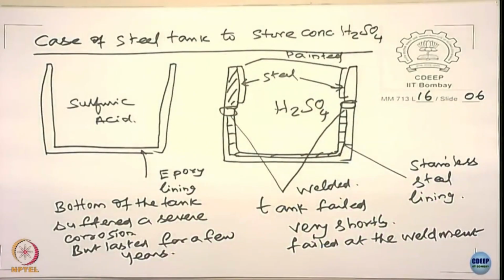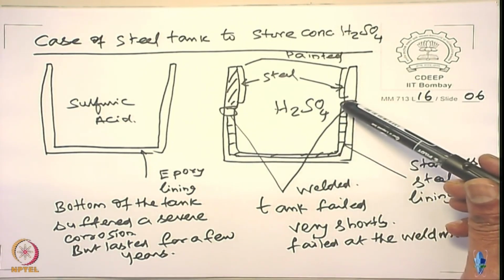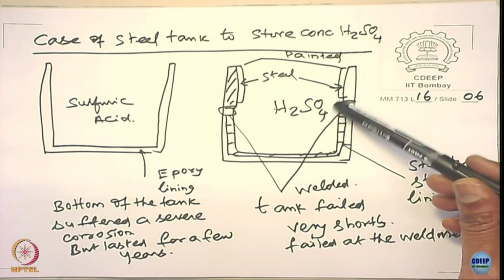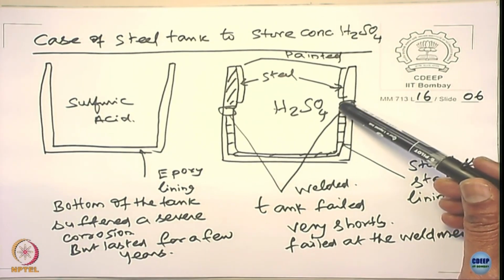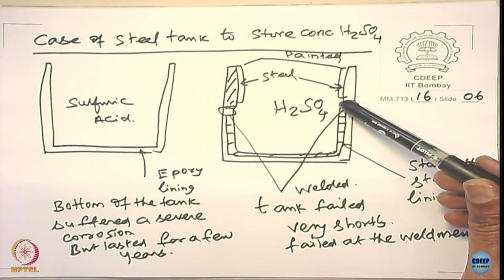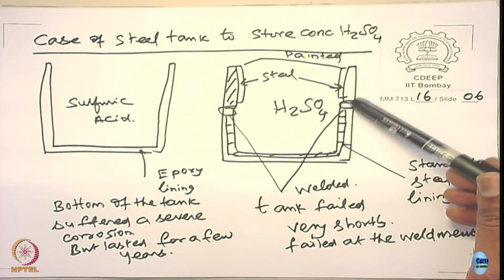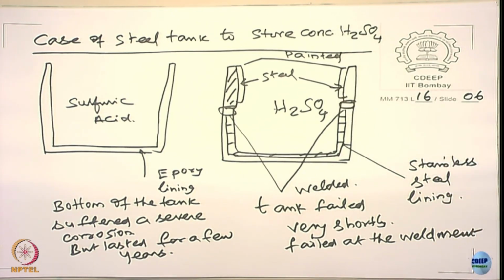Very interestingly, the guy diagnosed saying that the painting is bad, and so the tank failed because the corrosion occurred at the paint, and this place is welded here, right? And you weld it, and painting is always difficult at the welded location, right? Normally you grind very nicely and then you paint. So the person said that, oh, the failure happened because of improper painting, and they went on to say that we should redo the painting. But some wisdom prevailed and they tried to look at why it failed.